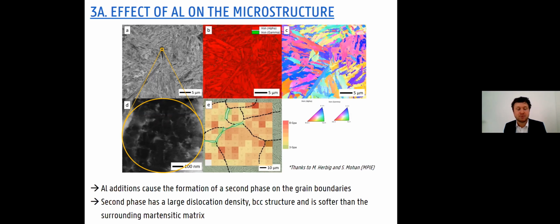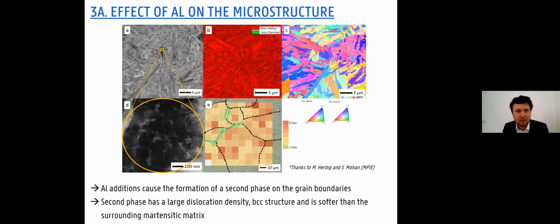How did we tackle that? By performing nanoindentation. As can be seen in picture E, you can see 100 indents, which are separated 10 microns from each other. This comes down to a certain hardness value, indicated by the color map, going from 3 to 8 gigapascal. If we then plot the prior austenitic grain boundaries in black, we can clearly see that there are green regions, and these green regions come with a softer phase. They are indeed the locations where we observed the open spaces on the previous slide. So these open spaces in between the prior austenitic grains are a ferritic film, and they make it softer.